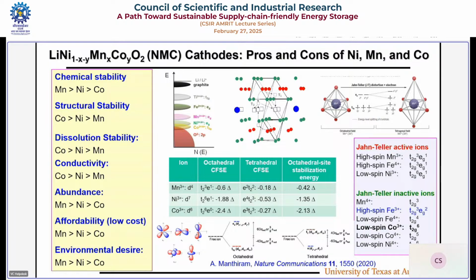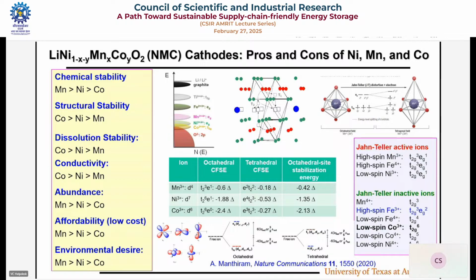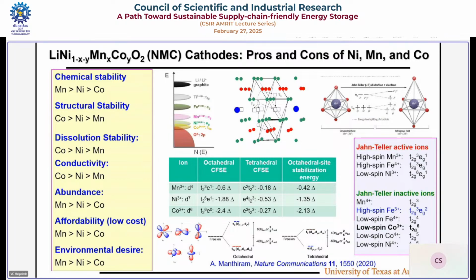I cannot use lithium cobalt oxide more than 50% of its capacity. Capacity is limited. I call it chemical instability. If I take manganese well above the oxygen 2p, I have all kinds of manganese 4+ oxide, MnO2, alpha, beta, gamma, epsilon, lambda, so many things are there, no problem. Nickel, barely touching. It's in between. That's the point number 1. For that, manganese is good, cobalt is not good. Chemical instability. The next factor is structural instability.